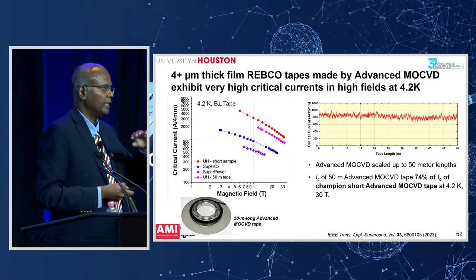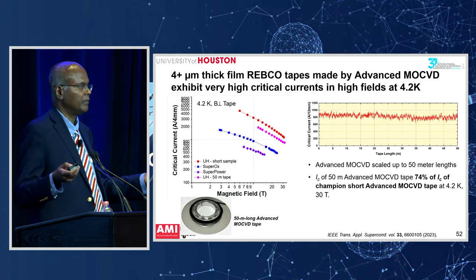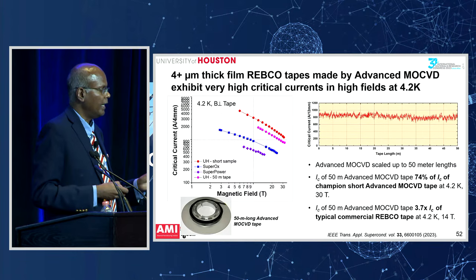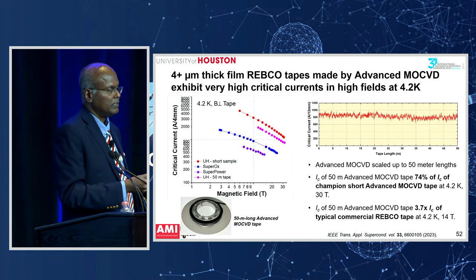So you can see the 50 meter tape is already performing at about 74% of the performance of a short sample, which is pretty good, and it's about three times better than what industry makes. So we're showing that this technology is not just something lab scale, but can actually be taken to manufacturing also.